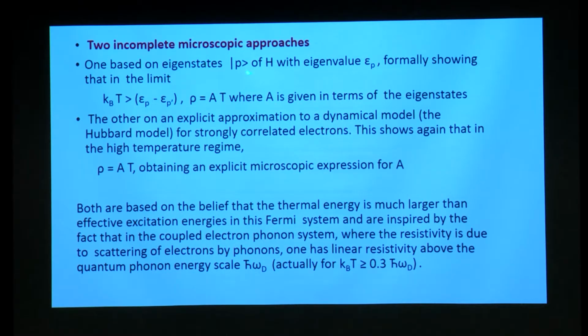The other calculation, which is also incomplete, is based on an explicit approximation. It's a dynamical model. So, I take a very simple dynamical model, the Hubbard model for electrons on a lattice, and make an approximation to the solutions of this model for strong correlation. And from that, I infer that the resistivity at high temperatures should again be linear in temperature with a coefficient A, for which I obtain an explicit expression in this dynamical model under a particular approximation.